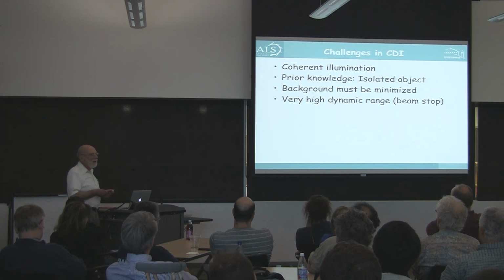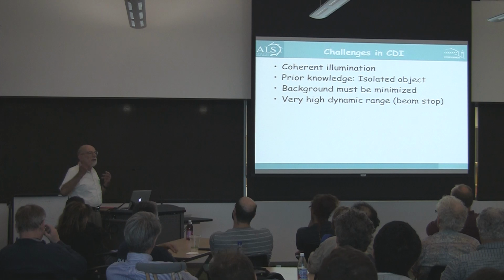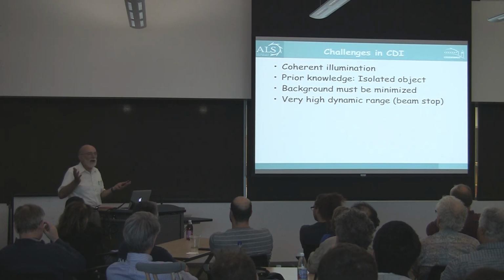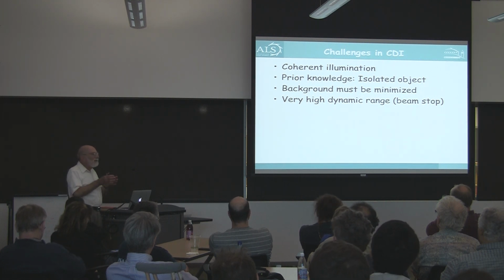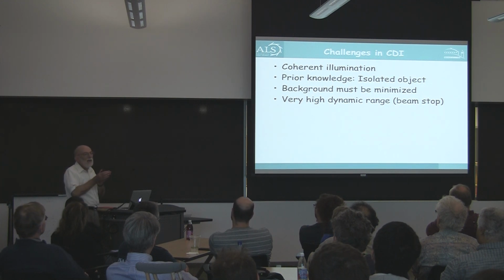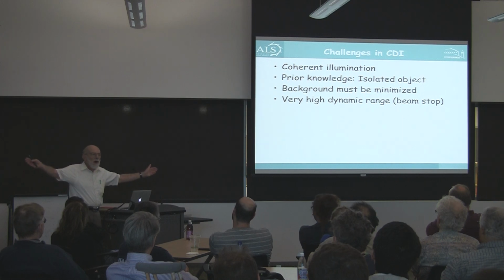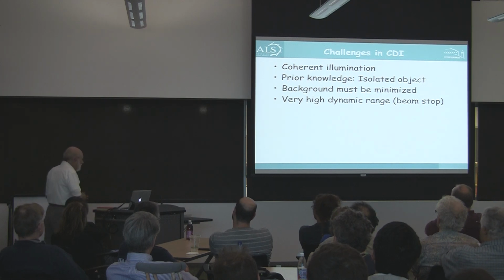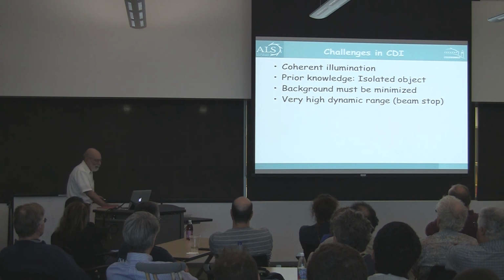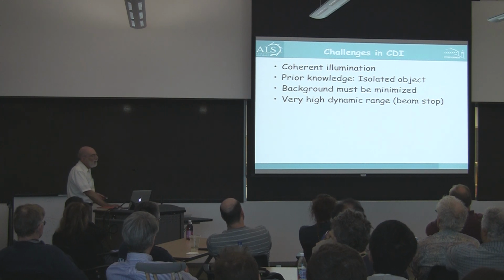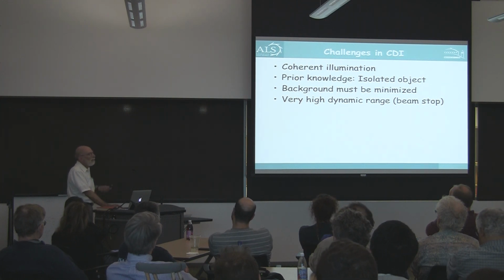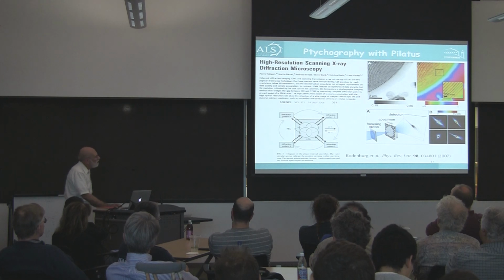Then the other problem is that you somehow have to make sure that your detector doesn't get any signal other than the diffraction from your isolated object. Very hard to do. Furthermore, the diffraction pattern is extremely intense right in the direction of the beam and gets to be very weak when you go off at high angles. So this turned out to be a rather daunting set of criteria, and relatively few people today are pursuing this at synchrotron light sources.